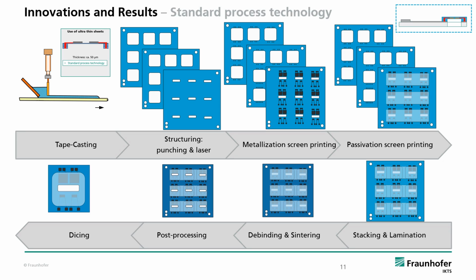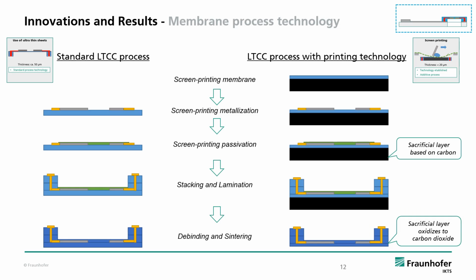Let's compare the standard process to the additive process done by screen printing. In that case, a sacrificial layer is necessary to carry the membrane. You can see the important steps for both fabrication processes in a cross-section scheme. Left, you can see the standard process with ultra-thin tape, and on the right the LTCC process with printing technology.